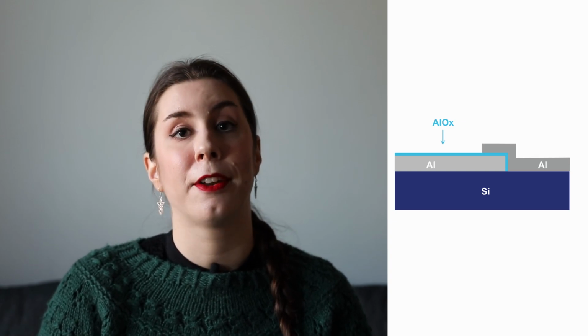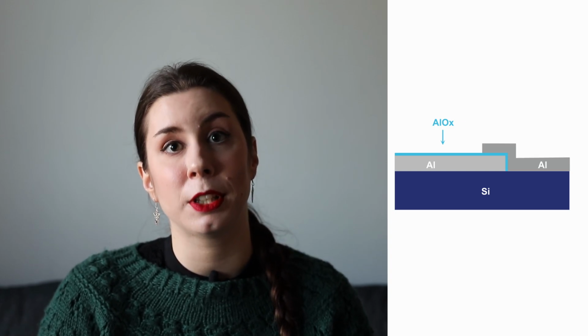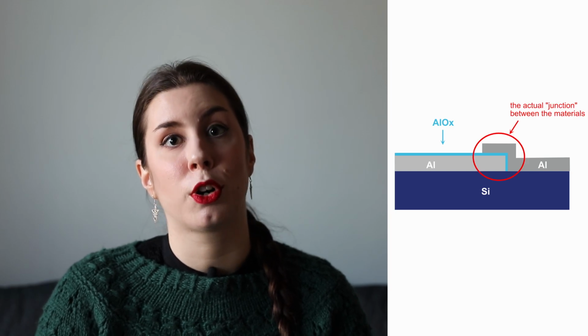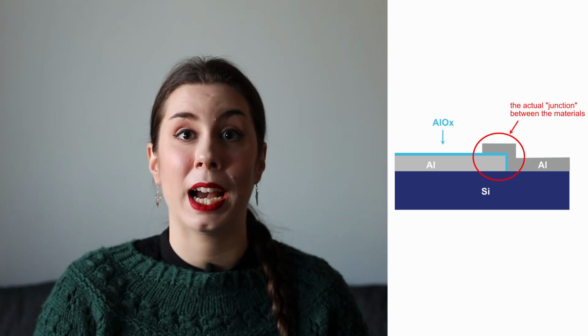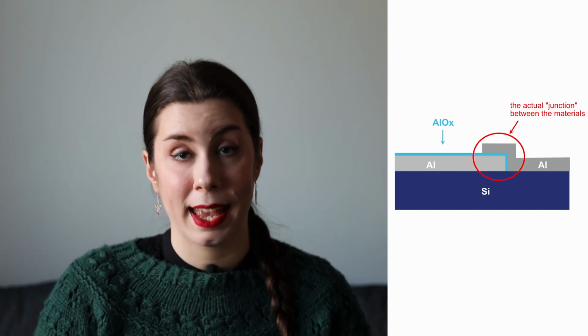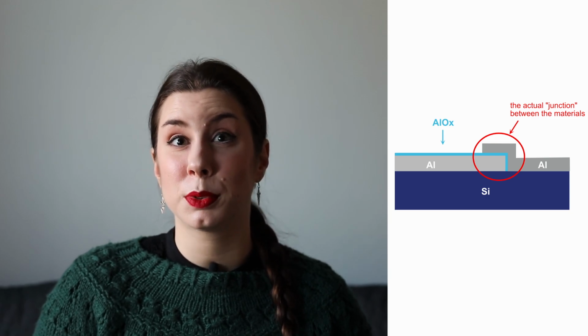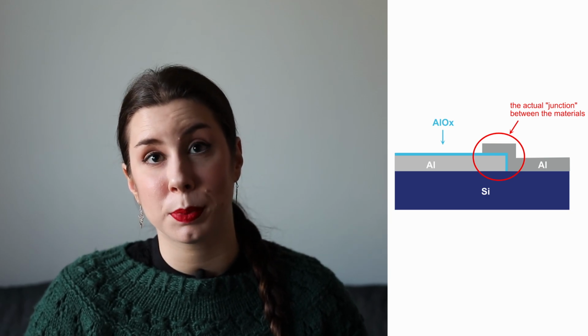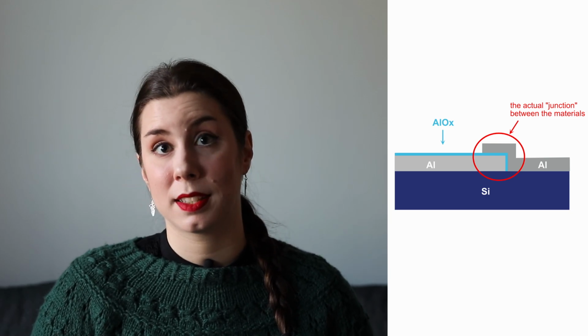The way we grow these junctions is quite straightforward. We will first deposit a layer of aluminium to form the bottom electrode, then we will flood the deposition chamber with pure oxygen to grow a layer of aluminum oxide on top of this bottom electrode, and finally we will deposit another layer of aluminium on top of all this to form the second electrode. How we actually define the circuit on the wafer and how we make sure everything is where it's supposed to be and is also connected the way it's supposed to be gets a little more complicated.